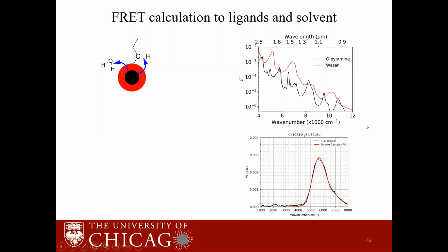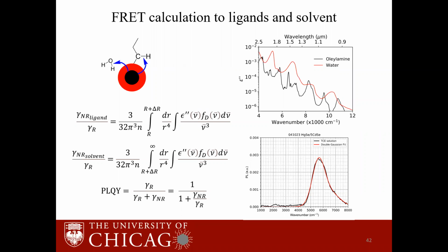So this is our FRET calculation. So we have, this is the formula for FRET between an absorber and an emitter. We have the absorption from either the ligands or the solvent, which we have measured experimentally. And we have the emission spectrum of the quantum dots. So we fit that to a Gaussian and plug this into an integral to do an integral over the frequency.